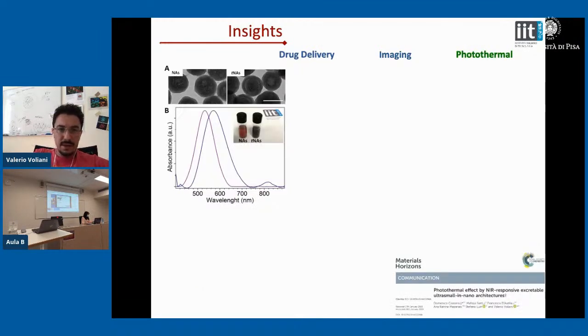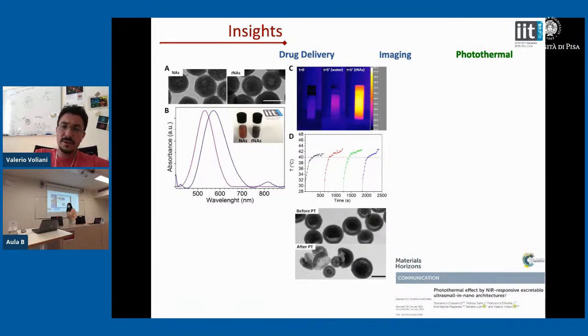Moreover, with a very small change in the synthetic protocol, we are able to produce some plasmonic bands here in the infrared part of the spectra. By irradiating on this band, our particles heat up. And very interestingly, even after many cycles of heating, the ultrasmall particles still remain ultrasmall, so they do not aggregate or reshape. So the excretion ability is still maintained.